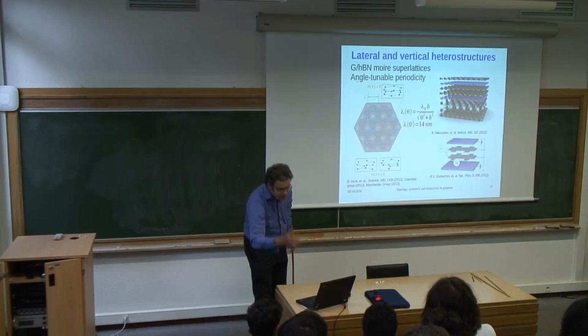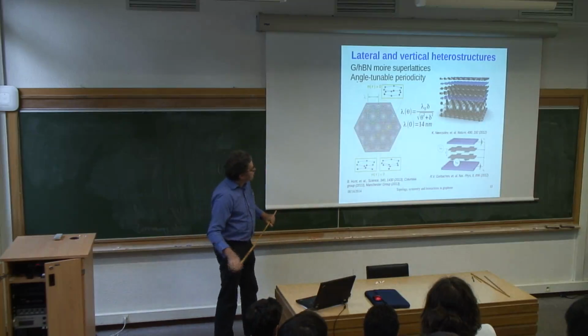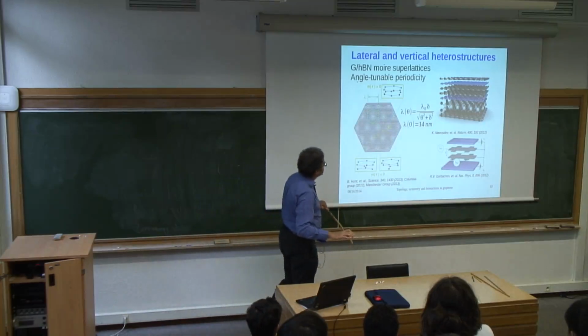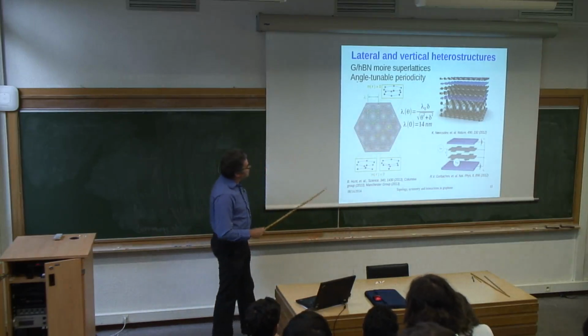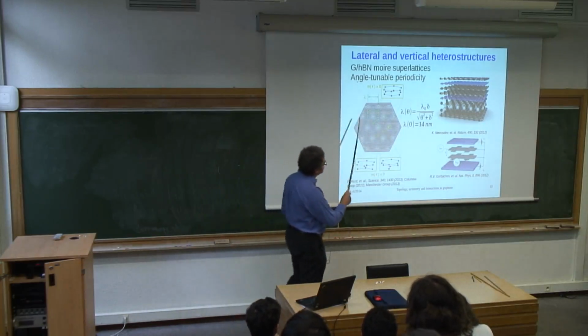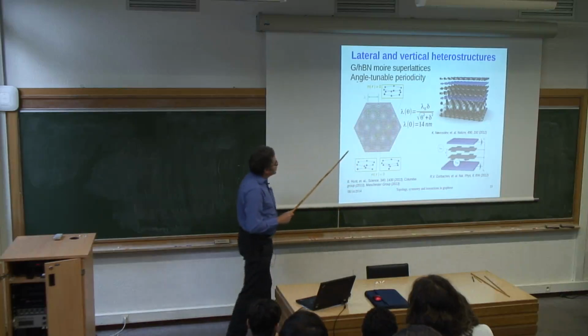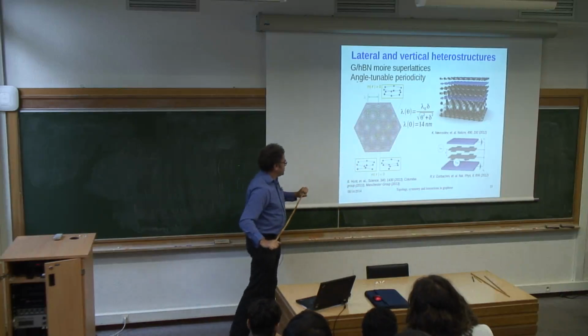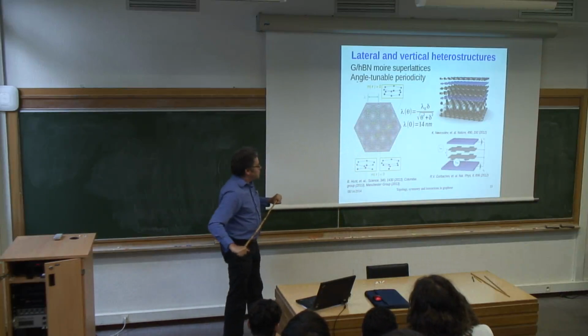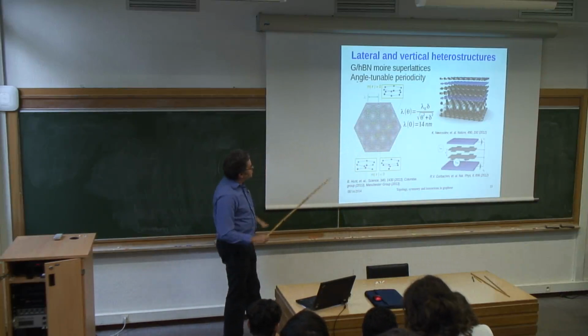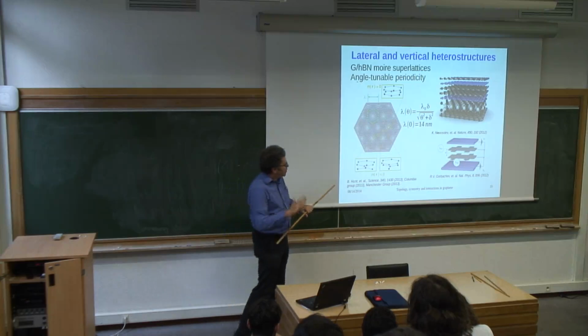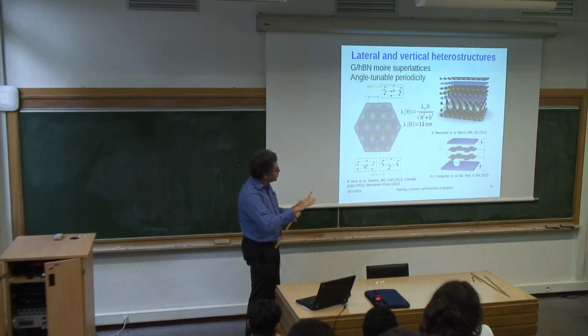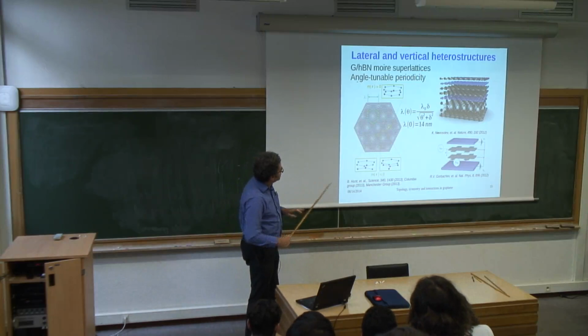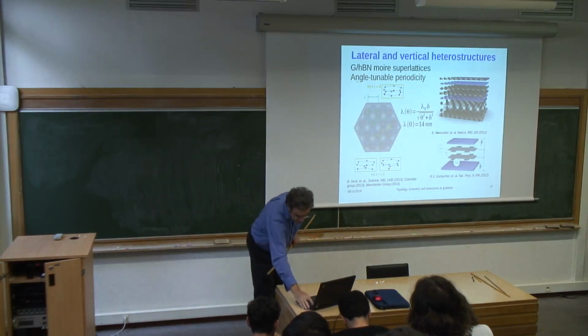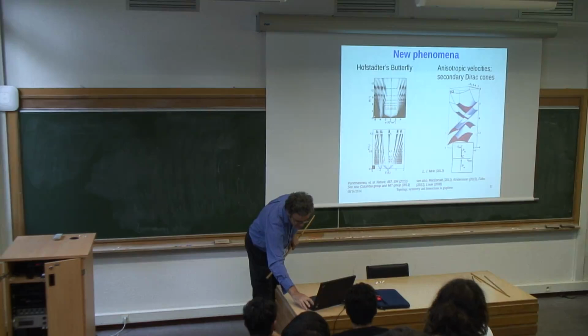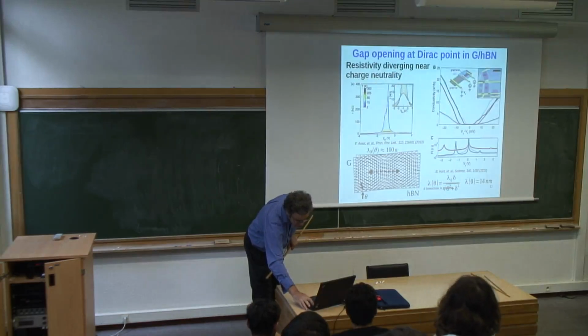Right now, if I'm interested in a real system, graphene on boron nitride, then I have to take into account the period mismatch that leads to a superlattice structure, and that means that if I try to introduce a mass term in my Hamiltonian, then it won't be spatially uniform. It will be spatially modulated with that period, and so I have to extend RG to treat that.